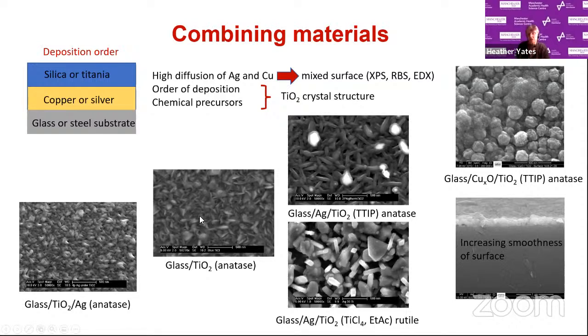However, if you put the silver down first on the glass and then put the titania, on the top image, you can see little light colours, which are the silver that's percolated through. But depending on which chemical I use for the titania, if I use titanium tetraisopropoxide, you get this anatase structure. And if I use a different material, titanium tetrachloride with ethyl acetate, you get this rutile structure. So what you put in makes a huge difference.